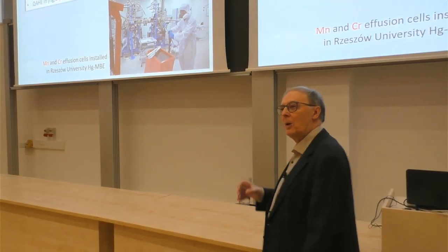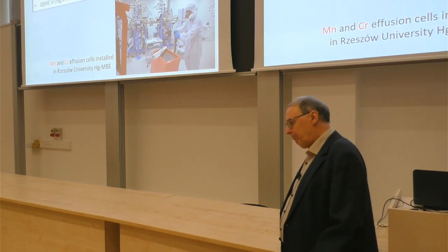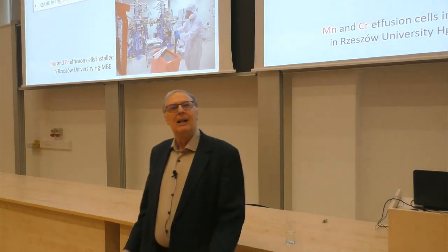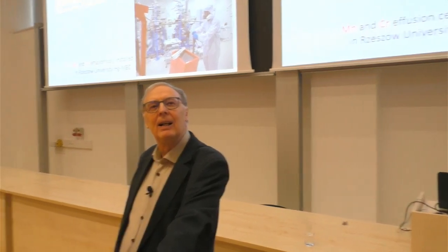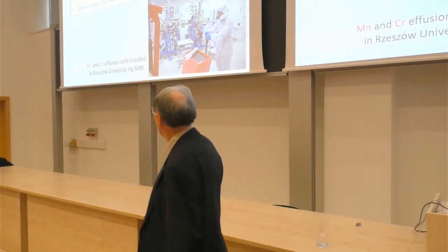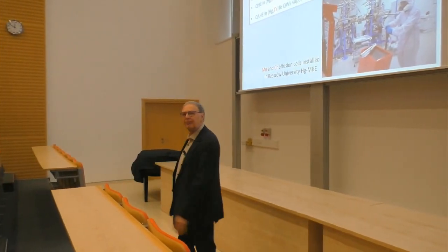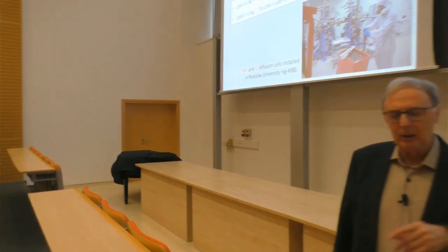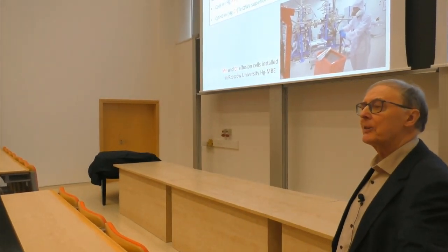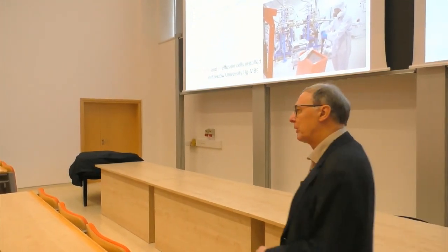Maybe I can start. You mentioned these materials, can you elaborate a bit more about which concentration of manganese and chromium would be optimal for such a standard? Manganese enters very easily. We can put as much manganese as we want. For this mercury manganese telluride standard, we need about 1% of manganese. Very little. Already this is enough to produce a very nice, beautiful quantum